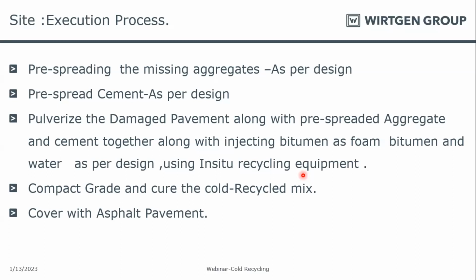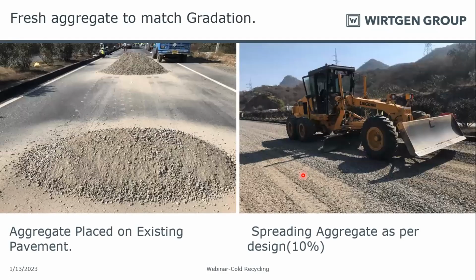This is the execution process. As you can observe from the pictures, first we pre-spread the aggregates as per the mix gradation. Then we spread the cement using the microprocessor controlled cement spreader. Then we pulverize the existing damaged asphalt layer with the addition of bitumen as foam and water as per the mix design. Then we grade it and compact as per the design, and on top we cover it with the asphalt layer. These are some job site procedures. On the existing asphalt layer we spread aggregates as per the mix gradation, and we grade it with a grader.